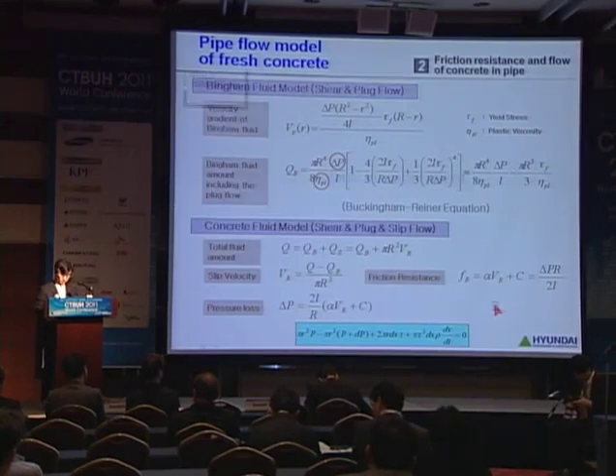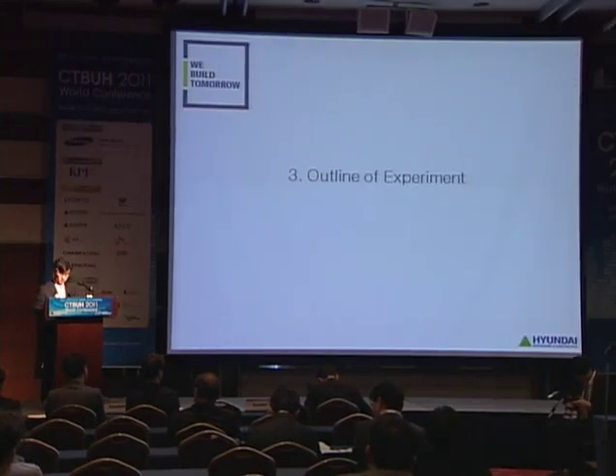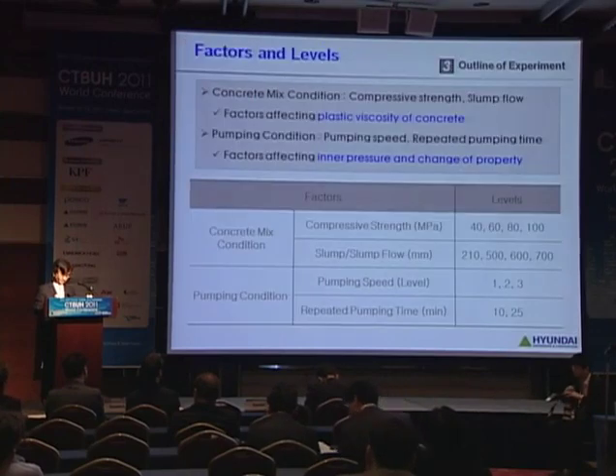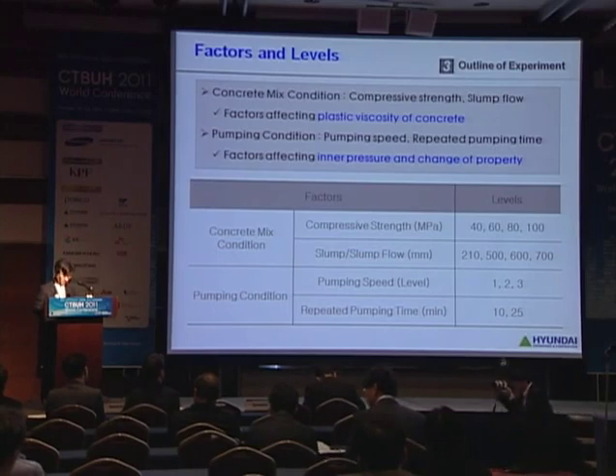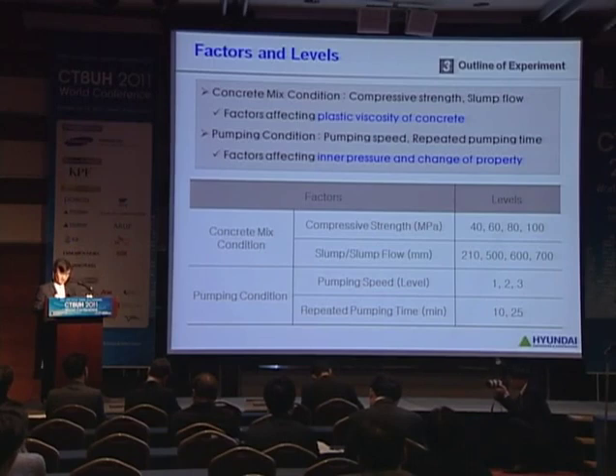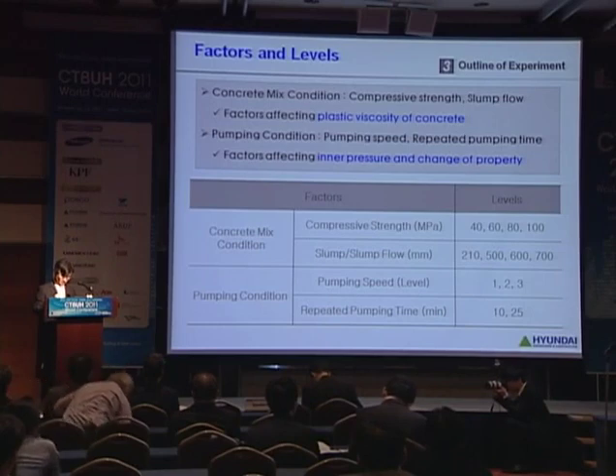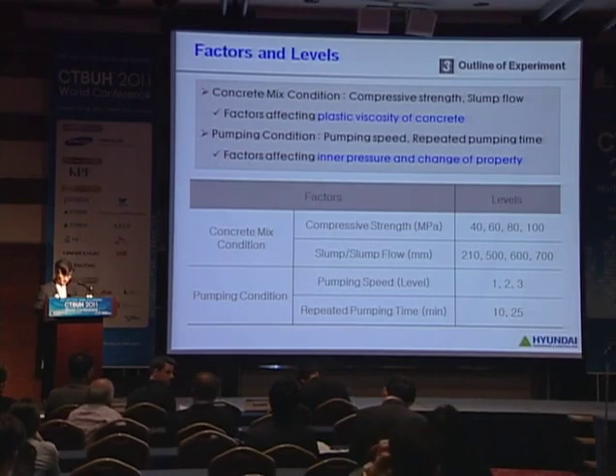The next is outline of experimental plan. First, experimental factors and levels. To find the influence of concrete fluidity on pumping pressure, compressive strength and slump flow were set as factors for concrete mix condition, and pumping speed and repeated pumping elapsed time were set as factors for pumping condition. 4 levels of compressive strength, 40, 60, 80, and 100 megapascal were applied.